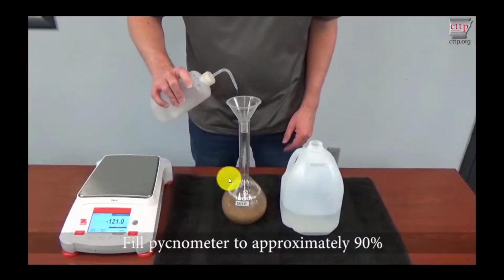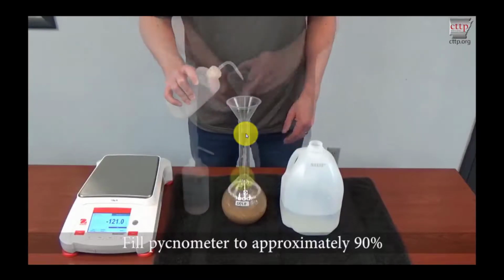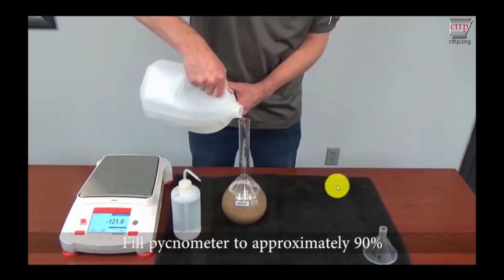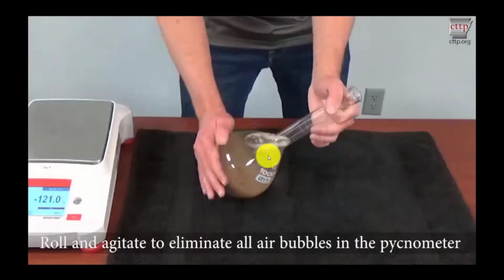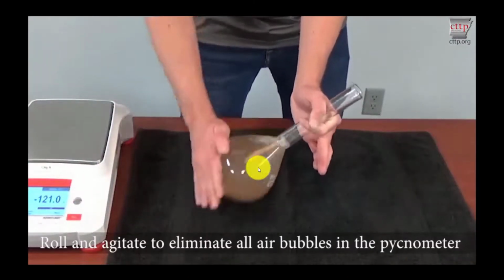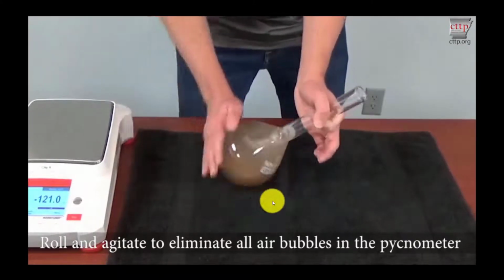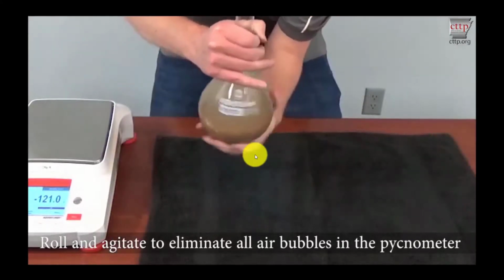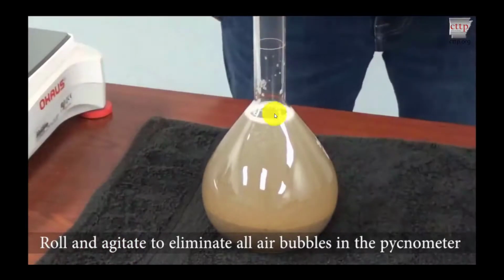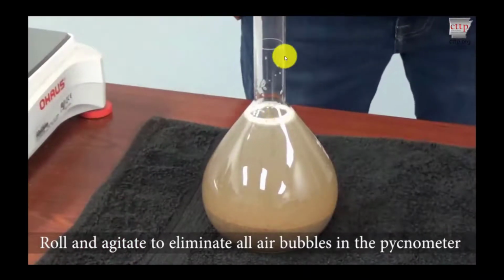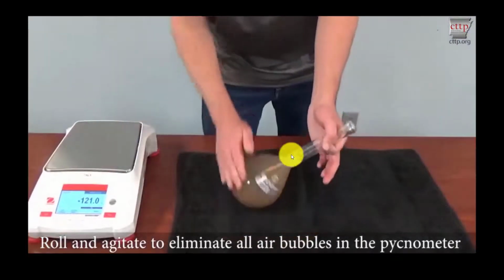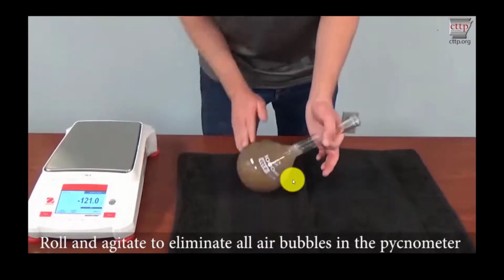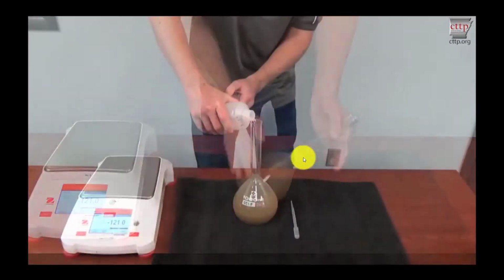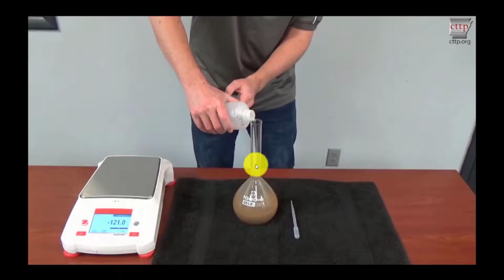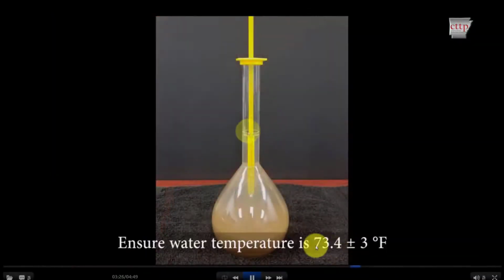Over here, the SSD weight of a fine aggregate has been added into half liter water, and then you remove any sort of bubbles present in it, so that it can give the accurate result up to this marked value. After doing so, you will add a little more water so that it will reach up to the level mark. You must ensure that it is at 23 degrees Celsius, 73.4 Fahrenheit.